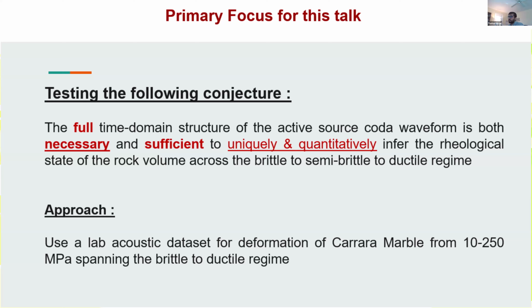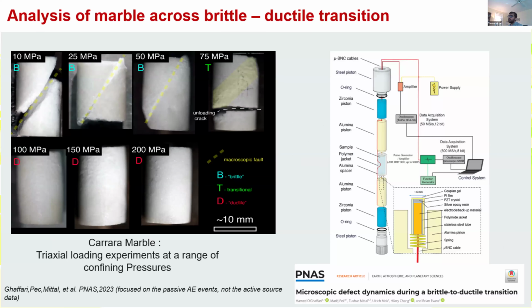So the approach is going to be to test this conjecture. We're going to use a lab acoustic data set for deformation of Carrara marble, spanning confining pressures of 10 to 250 MPa. The reason for using marble is that as we go from 10 MPa to 25, 50, 75, 100, 150, 200, we can span the whole regime from more brittle dominated behavior, where you start getting faulting, to transitional behavior with semi-brittle deformation, to more ductile deformation. You can see that in these images, which show what the sample looks like at the end of the experiment. In the brittle regime, we get a nice clean fault forming. You don't see that in the ductile regime, but the sample overall starts to deform.